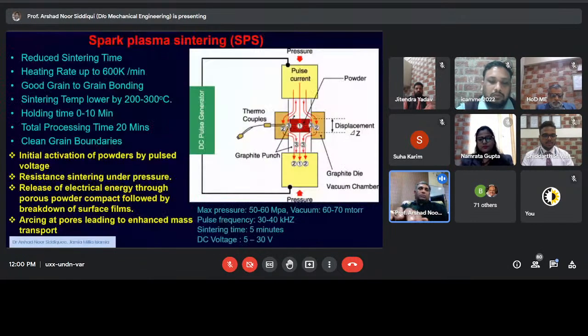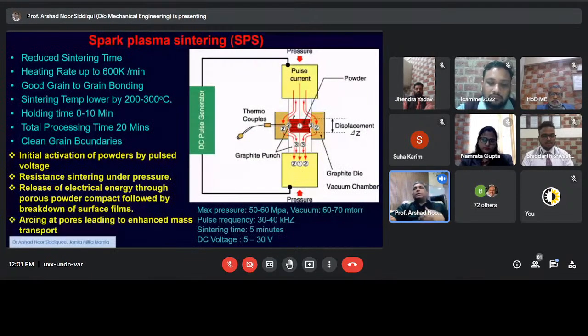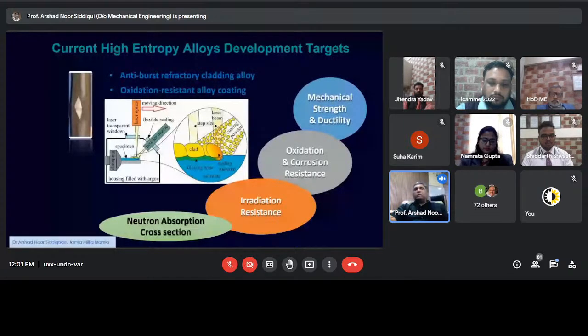One of the most important methods used thus far for manufacturing high entropy alloys at the laboratory scale is spark plasma sintering. It has several limitations, but a huge number of advantages vis-a-vis conventional manufacturing methods like casting. It is faster and quicker. But the problem is that it requires a lot of iterations. You make it once, then repeat it 3-4 times, and only then can you homogenize and come out with high entropy alloys.